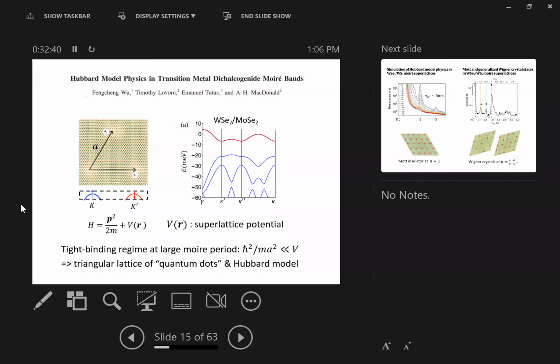This is really a textbook example of solid state physics. You have a kinetic energy, p squared over 2m, and a periodic potential. The difference here is that this potential is a long wavelength potential. It has the period of the Moiré superlattice, which is typically a few nanometers. And this mass is the effective mass of the TMD semiconductor, which in this case is actually quite close to the free electron mass, which just turned out to be a property of WSe2.